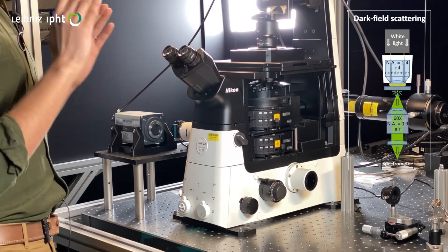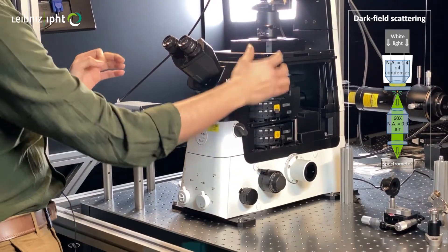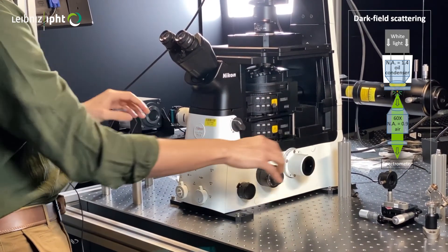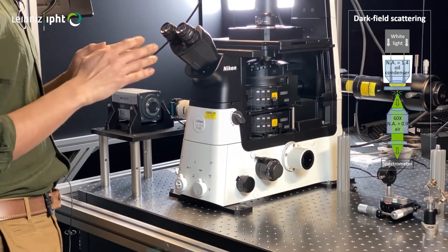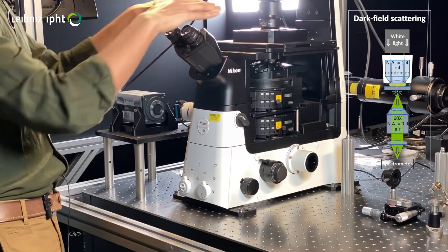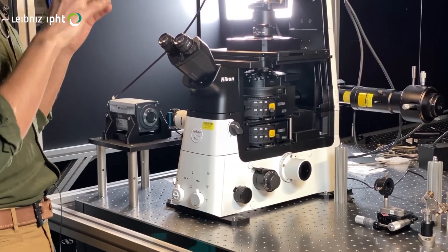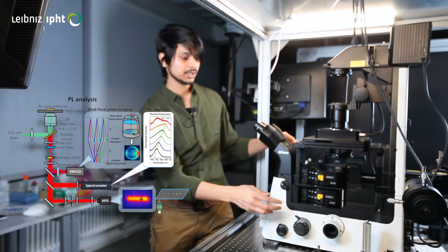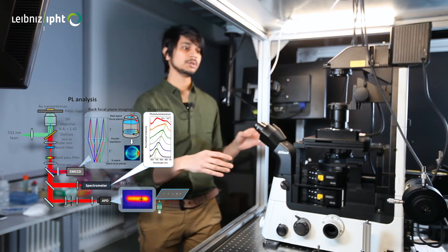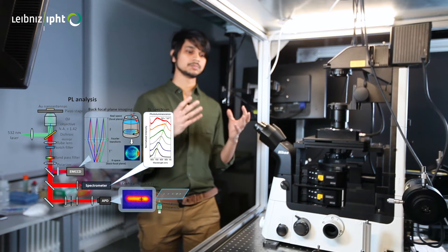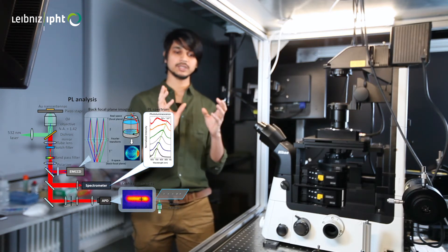Each one of these plays a very crucial role in the study of DNA nano antennas. For example, the dark field image is used to locate the nanoparticle as well as do the spectroscopy on them — we can tell the resonant wavelength and where the particle is. Then we record a photoluminescence mapping. We invert the sample, shine the light, and it helps us to see the photoluminescence image from the particle and locate the axis of the nano antenna precisely.